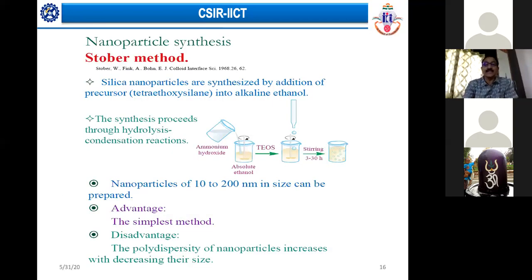This is a general thing, but I'll show you one example, the Stöber method of synthesis of silica. It's a robust method where you can control the size of silica particles and have uniform particles of silica, anything between 10 to 200 nanometers. The precursors used are ammonium hydroxide, absolute ethanol, tetraethyl orthosilicate, which is the silica precursor, and a few drops of water, and you stir it for 3 to 30 hours, and you end up getting dispersed silica nanoparticles. People who want to synthesize silica nanoparticles can make a note of this article, as it gives a very good idea about the synthesis. I myself have used this in my work. I will show in my slides how, by making a little difference in the precursor ratios, we could synthesize these materials in different sizes.